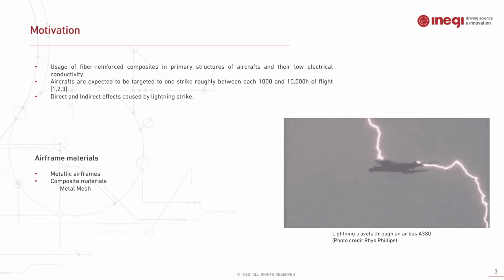One of them is the commercialized solution of incorporating a metal mesh on the outer skin of the fuselage. Another could be metallized fibers, by covering the substrate of the fibers with conductive metals like nickel or copper. Or it could be nanofillers, by incorporating carbon nanotubes or graphene in the resin, or incorporation of metallic